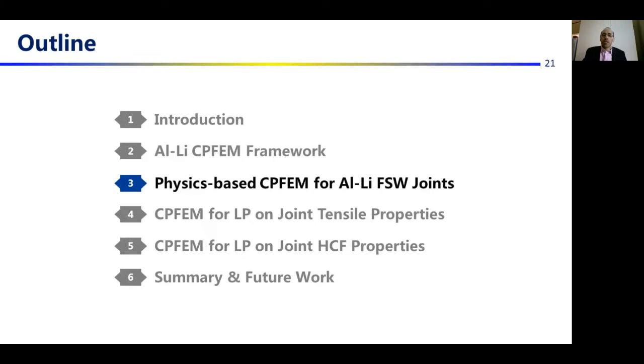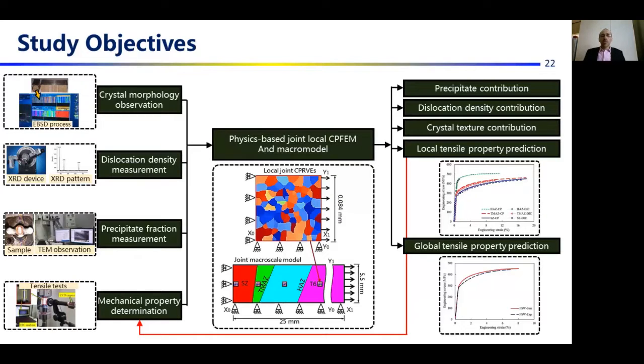Now the physics-based CPFEM model for aluminum-lithium FSW joints. In this study, joint local physics-based CPFEM models are developed by including the material microstructure attributes such as crystal morphologies, dislocation density, and precipitates, and the developed model quantifies the strengthening contribution of these microstructural attributes to predict the local and global tensile properties of FSW joints.